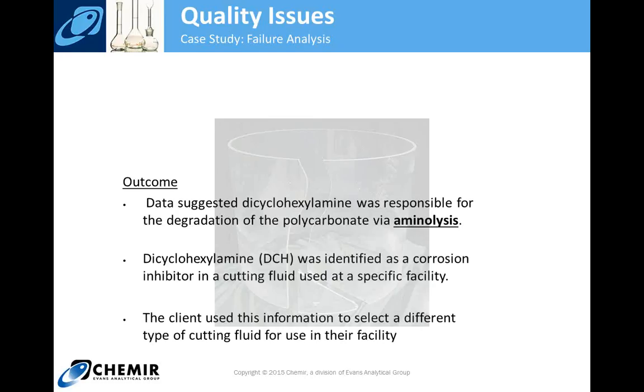And again, this kind of information comes from discussions with the client. So if you're one of our clients, this is some of the dialogue we had back and forth, explaining some of our analytical results, trying to get a cause and effect, and through discussions with our client and our client talking to their client that had these issues, finding DCH is used in cutting fluids at the specific facility. This facility ran 24/7. If you ever cut metal, you know it's a hot process, and the semi-volatile DCH was volatilizing from these cutting fluids and condensing in different places, including on the polycarbonate, and causing this degradation.